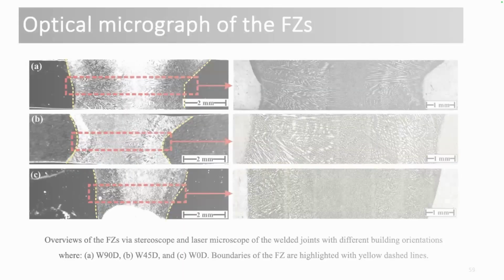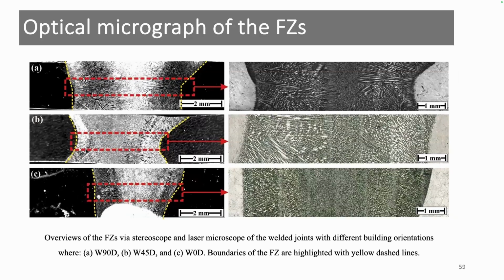For the TIG welding processing, you can see that the microstructure of the fusion zone is totally different. Here, we cannot see that type of cellular structure. We already used filler metal, and this filler metal here shows like a duplex structure of austenite and delta ferrite. Furthermore, when we also compare the size of the fusion zone here, we find that in the 90 degree, the width of this fusion zone about 6 millimeter, while here in the 0 degree, it was about 4 millimeter.